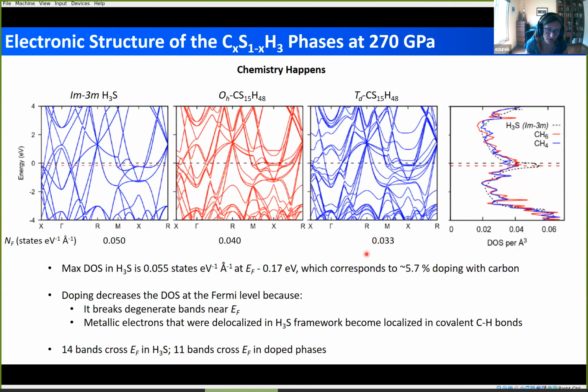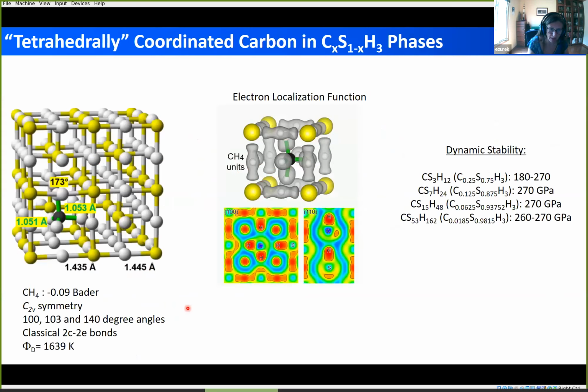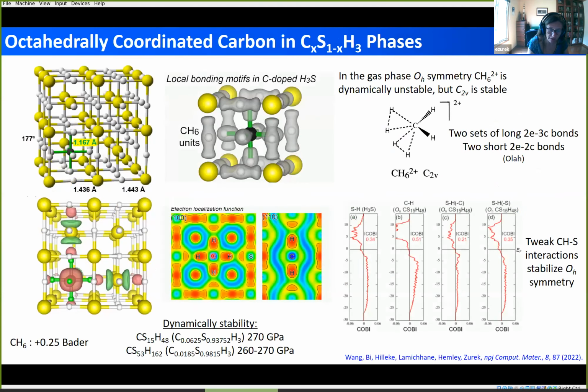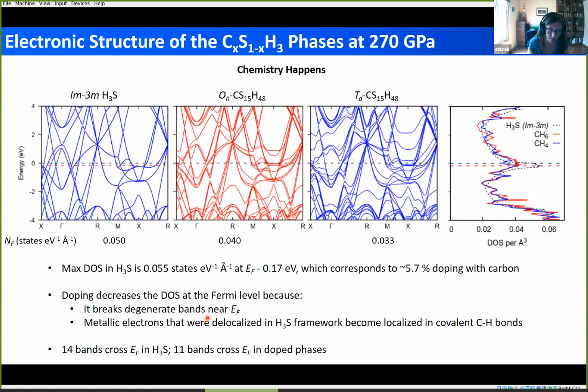The reason for this is a few things. First of all, the doping actually breaks degenerate bands near the Fermi level by changing the hydrogen-sulfur bond distances. Note that the carbon-hydrogen states are not at the Fermi level. Also, you're localizing these electrons that were previously metallic into these types of covalent-type bonds. So we're going to be changing the density of states due to this reason.